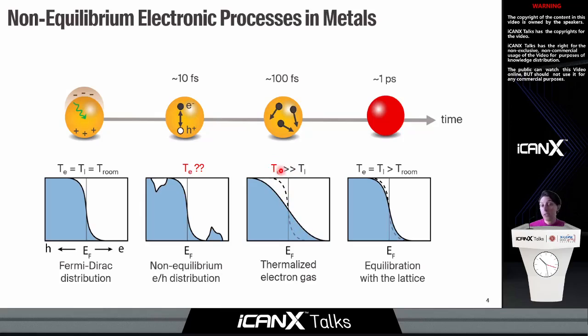They can be of the order of thousands of kelvins without the particle melting, because this is still a non-equilibrium situation in which the lattice has not yet been involved in the process. And it's only on the picosecond time scale that the electrons eventually transfer a lot of energy to the lattice, and therefore we will observe a Fermi-Dirac distribution with an elevated electron temperature compared to the room temperature. So we are particularly interested in these two processes because, as you can see here, if this is our energy axis, we have the possibility of generating a population of electrons or holes that have very high kinetic energies compared to the initial Fermi-Dirac distribution.